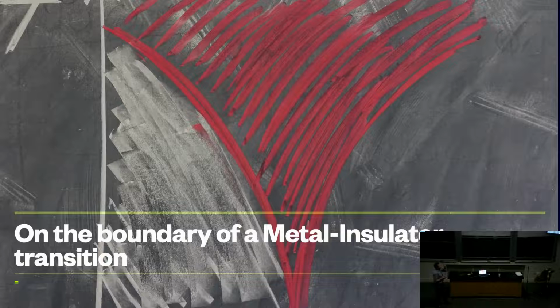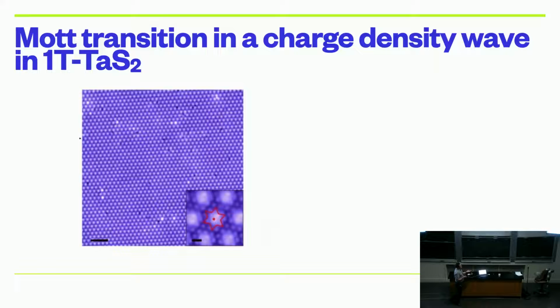Okay, so I wanted to look at another system where this idea applies. It's okay to have your biases as a scientist, as long as I have my preferred ideas and I'm going to pursue them, even if they're wrong. But I was going to try at least this one other system, which is on a metal insulator transition. This is 1T tantalum sulfide, and the system forms a different kind of order. It's not magnetic, it's called a charge density wave. And it turns out that if you slow cool the system, it forms this nice pattern. This is an STM pattern, and it's an insulator. But if you quickly cool the system, it actually forms a metal. So that's kind of neat.